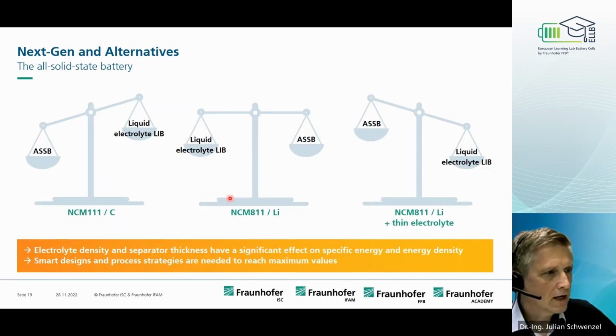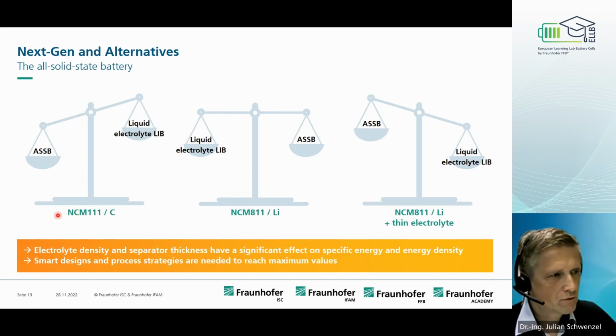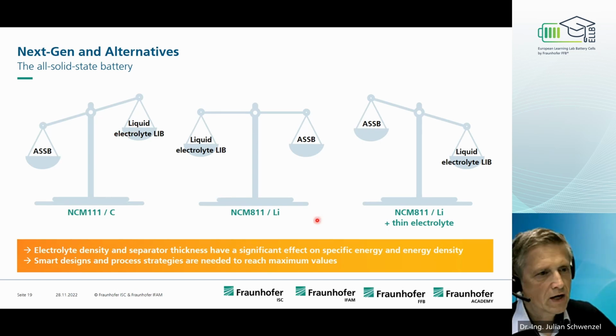So I would like to give you this key message. Solid-state batteries are very attractive, but if you use the classical cathode materials I mentioned, the weight is much higher, so the solid electrolyte-based system is heavier. So we have to use lithium metal and high voltage cathodes. At cell level, or if we also make a thin electrolyte with less material, we can really improve the energy density of this solid-state battery technology.